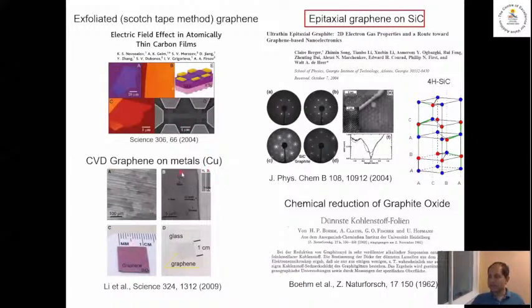There's also CVD graphene, which is different. Here, what you do is you take copper foil, put it in an oven, and at a high temperature, you flow methane, which is CH4, which has carbon and hydrogen in it. The idea is that the carbon decomposes and then forms a layer on your copper, right? And then you can remove the copper and isolate the graphene. And then you can put the graphene on silicon dioxide, silicon, or on glass. So here you see this is the graphene, it's transparent. You get huge pieces like this. It's lower quality graphene than exfoliated graphene, but the sizes are much bigger. This is like 1 centimeter, that's like a few microns.